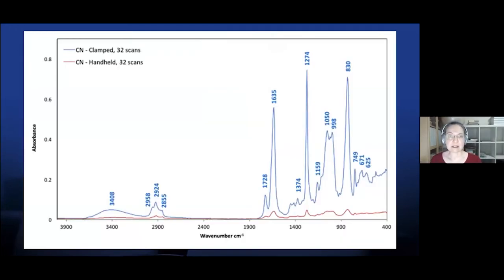This is a spectrum we obtained for cellulose nitrate, where you can clearly see with the blue spectrum that it's best to be able to clamp the material onto the diamond window to achieve really good contact. However, if it's not possible, it can also be manually pressed against the diamond window to obtain a reasonably good quality spectrum.